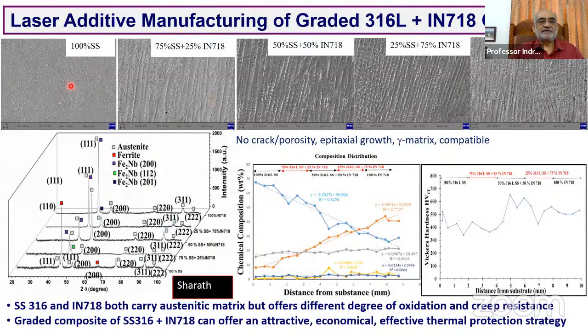So here is an example of what happens if I mix stainless steel with 718 and do a gradation. 100% stainless steel base substrate, 75-25, 50-50, 25-75, 100% Inconel. So I have a stainless steel component and I do compositional gradation, and then finally I have only Inconel 718. So I don't need a separate stainless steel, I don't need a separate Inconel component.